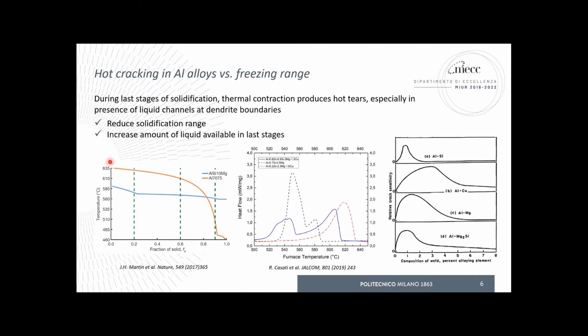This is a plot showing temperature against the fraction of solid. So fully solid is here, where the fraction is 1, okay? The very start of the solidification is right here, and temperature decreases. You can understand that for a well-processable alloy, aluminum silicon 10, the blue line, there is a flat portion of the curve in the very end stage of solidification, while a non-processable alloy, such as the 7075 alloy, usually has a very sharp drop in temperature in the last stage of solidification. So higher stresses, higher chance to get cracks.